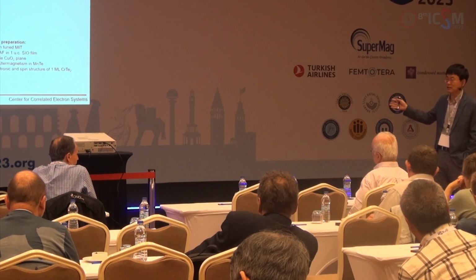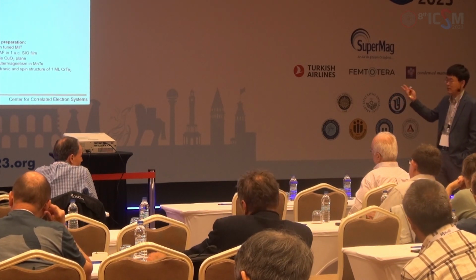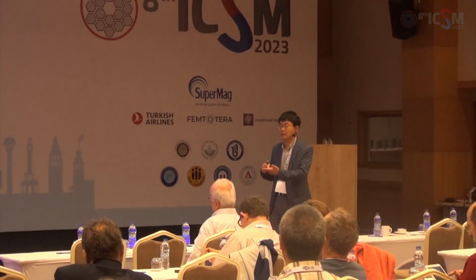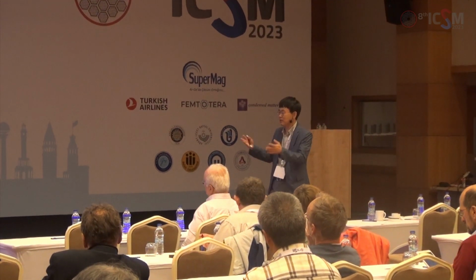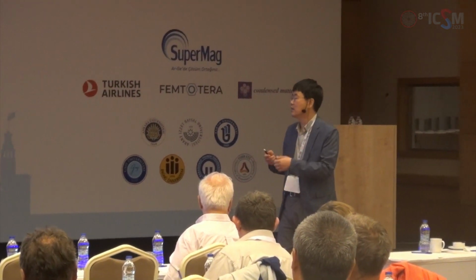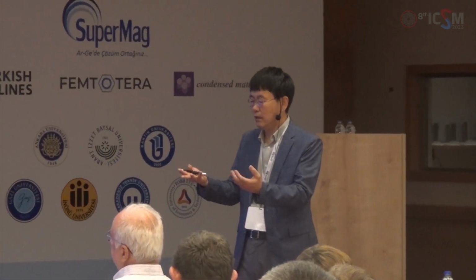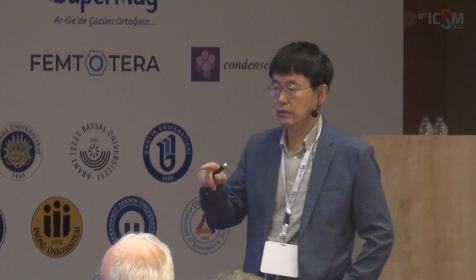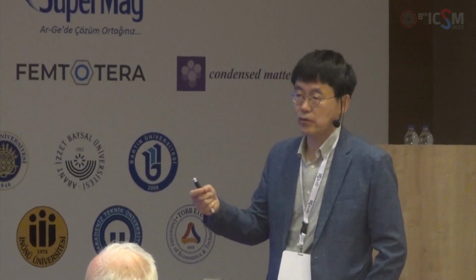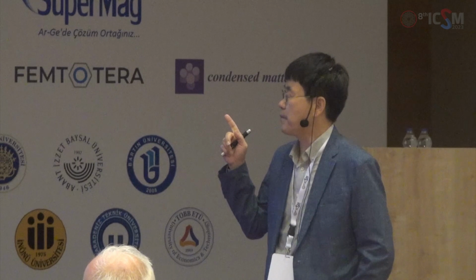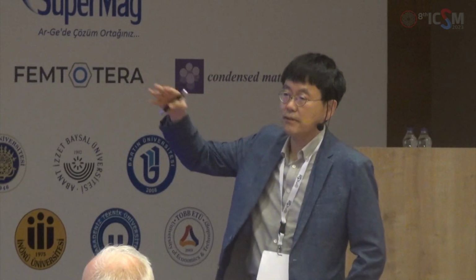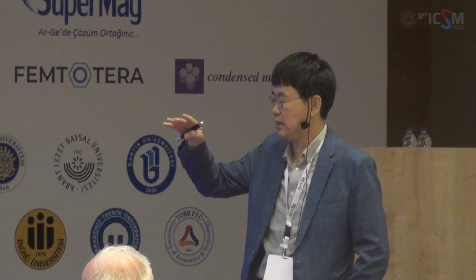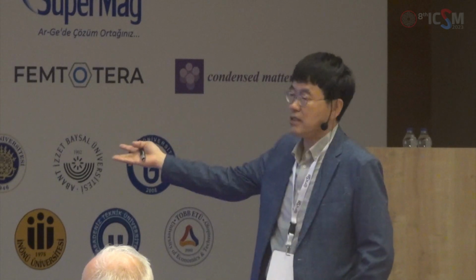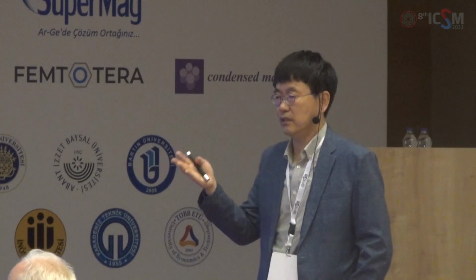Yeah. Okay, so here is one thing that I didn't talk about. Yes, that actually affects it. After the growth, we have to anneal the sample because there's a little bit of carbon on top, and we need to burn off the carbon by annealing in oxygen. So depending on this annealing condition, we can have different oxygen stoichiometry, as you might expect. We did that in different temperature steps, and there's an optimum temperature around 600 degrees C. So all these results are shown for the 600 degree annealed sample.